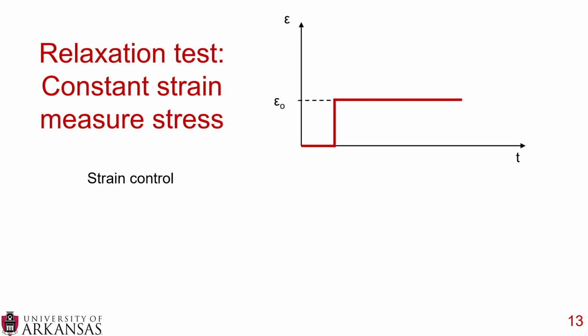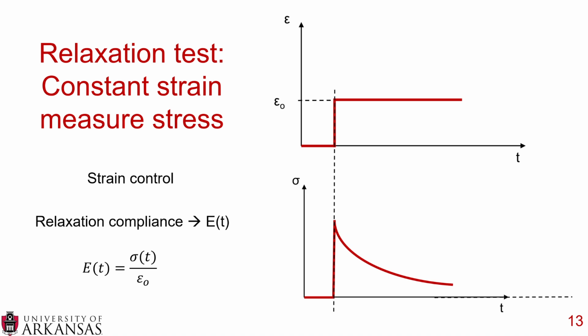This is called strain control. You have your sample, and at some point you apply a constant strain, and then you measure the stress. This is related to relaxation compliance, or E of T, which is the stress over time divided by that initial strain. When you apply that strain, there's a jump in stress, and then as you continue applying that strain at a constant level, the stress relaxes. Hence why it's called a relaxation compliance.